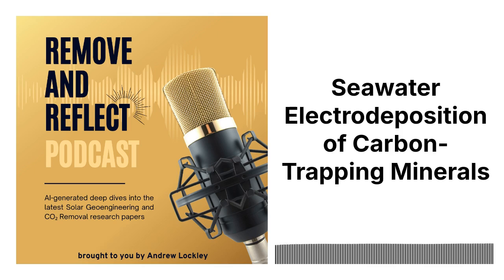So what did these synthesized minerals actually look like? Well, to the naked eye, they appeared as a white or slightly off-white powder with individual particle sizes ranging from very fine, around 0.02 millimeters, up to about 2 millimeters. Okay, so a range of sizes. Yes, and when they looked at them under a microscope, they saw some distinct shapes depending on the electrochemical conditions. While calcite tended to form more cubic-like crystals, aragonite had a more elongated needle-like structure, and brucite appeared as numerous tiny interwoven fibers. Oh, wow. So they look totally different. They do, depending on how they're made. It's really fascinating.